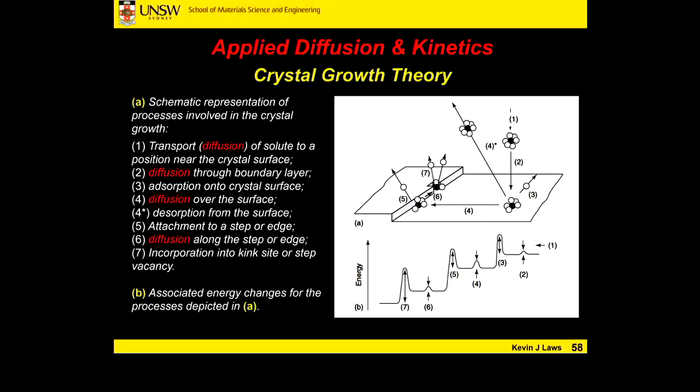We spoke about the process where our atoms or molecules have to first diffuse through our liquid or our primary phase to the surface of a growing nuclei. Often we have to attach to that surface, which involves a little bit of energy as well, diffuse across the surface and attach themselves to a low energy site if they have time. Again, the driving force for this entire reaction is the concept of something like undercooling.